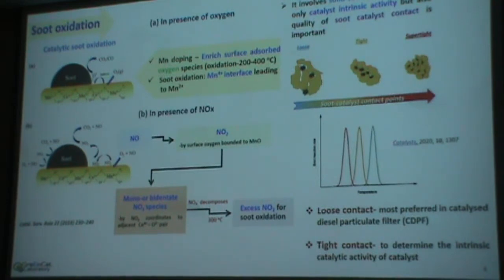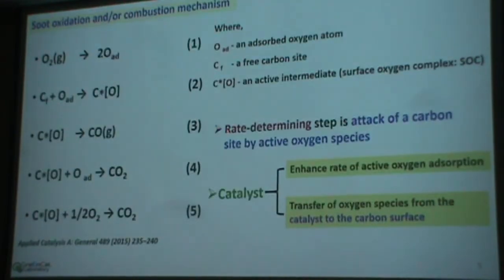In soot oxidation, as it is a solid-solid reaction, not only the catalytic intrinsic activity but also the contact between soot and catalyst plays an important role. Hence, different types of contacts have been used: loose, tight or super tight. It is obvious that loose contact has a smaller contact area compared to tight, hence the soot oxidation rate will be high in tight contact mode. Although that is true, in practical feasibility loose contact is more preferred. And if you want to know the intrinsic catalytic activity, we need to study the tight contact also. I have shown just the general mechanism.